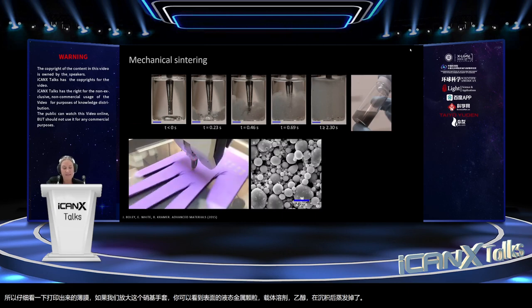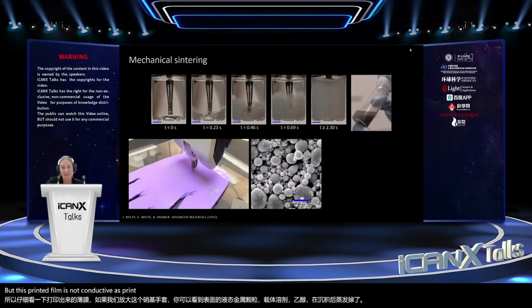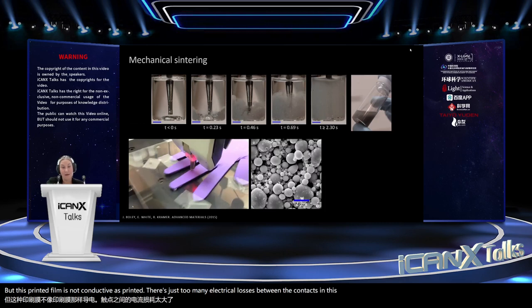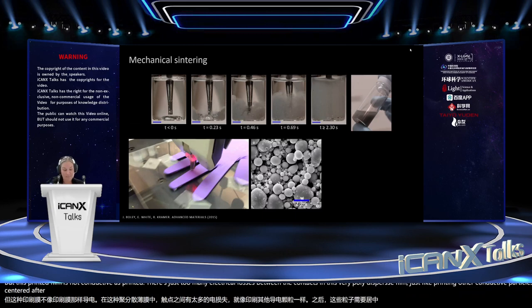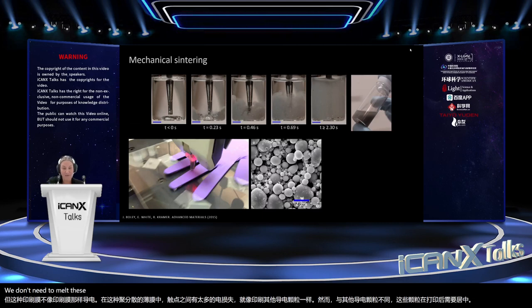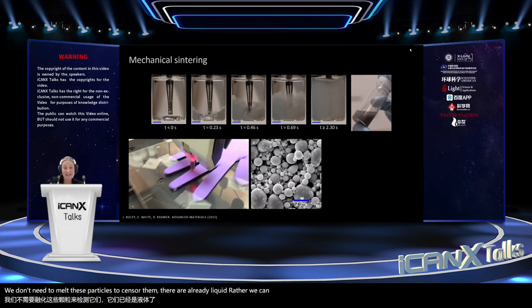But this printed film is not conductive as printed. There's just too many electrical losses between the contacts in this very polydisperse film. Just like printing other conductive particles, the particles need to be sintered after printing. However, unlike other conductive particles, we don't need to melt these particles to sinter them. They're already liquid. Rather, we can mechanically sinter the particles.